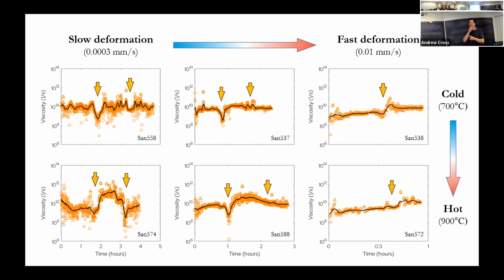And so what this shows is, well, it shows a couple of things really. It shows that phase transformations can produce one or two orders of magnitude transient weakening. We only see that as the sample is actively transforming, and then the strength recovers. So we do see the transient weakening, but it's mostly when we're slowly deforming the sample. And so it turns out, I think, that when your rate of transformation is fast relative to the rate of deformation, then you see more of an effect. Whereas if you're deforming really fast and the transformation is relatively slow, then you see less of an effect.